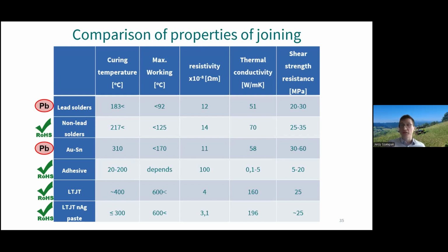But there is a disadvantage. This method requires at least 30 minutes joining time with applied pressure. It's quite a long time, but we built a press allowing us to create multiple sinter joints at once. With that, we lose concerning the sustainability because of the temperature of the process. But later on, with high thermal conductivity and high electrical conductivity, we're gaining due to the small losses of the energy.